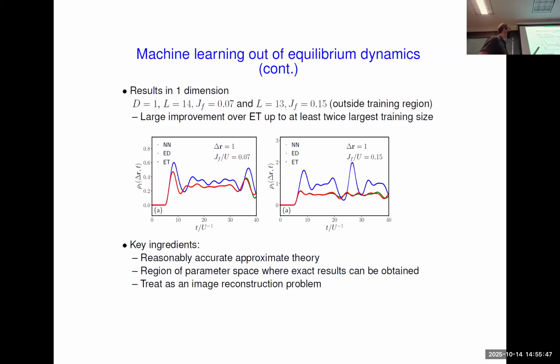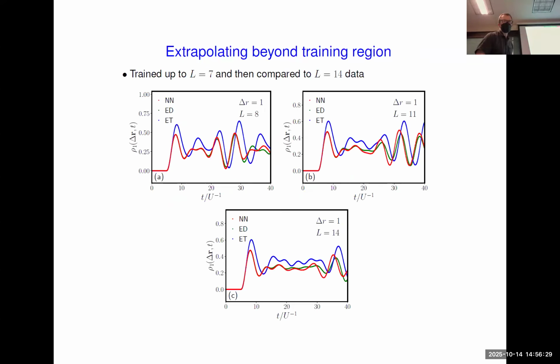And it seems that the key ingredients for having this scheme work are that you need a reasonably accurate approximate theory. If you input just a flat input, this doesn't work very well. You need to be able to find exact results in some part of parameter space, and then our approach basically treats this as an image reconstruction problem. So you're feeding in the blue image to match the green image. Our neural network can output the red image, basically. That's the way to think about this.